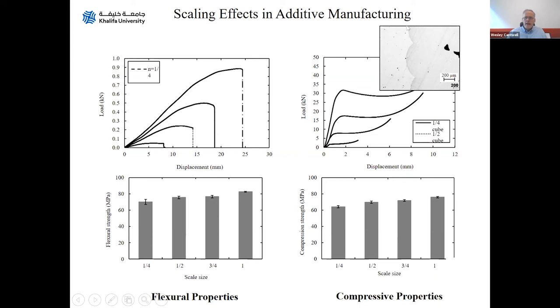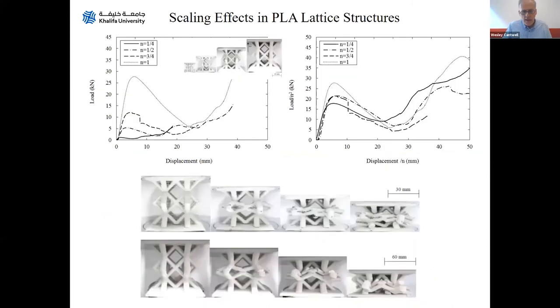We had a layer thickness here of about 0.5 millimeters, and you can see what are effectively defects on our surface. But nevertheless, we tested our lattice structures as well. We've got a couple of sizes here. I think these are the n equals half, n equals one. You can see the failure modes in them there. They're very similar as we change our size here.